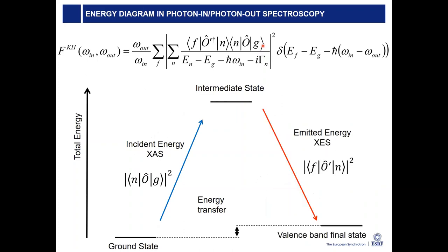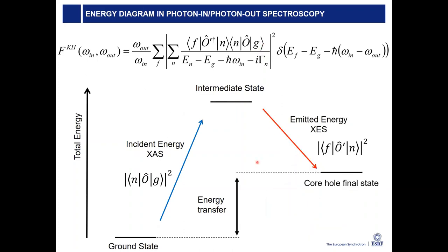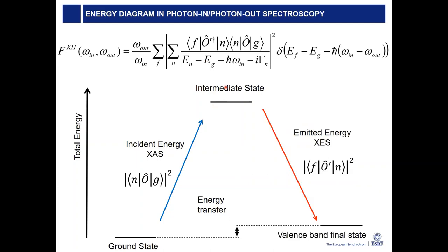But it's interesting, you can vary the so-called energy transfer. If you have a high energy transfer, you have a core hole in the final state as well, a shallower core hole than in the intermediate state. And you can reduce your energy transfer, and then you see actually very small energy excitations, and then your X-ray spectroscopy probes states that are similar to your optical.